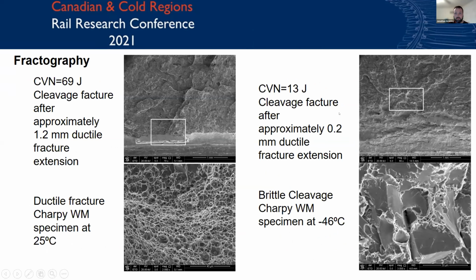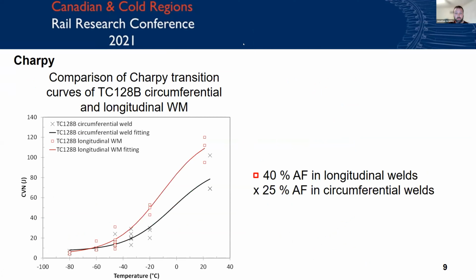So moving on, the next curve shows both the longitudinal and circumferential welds on the same figure, so we can compare them together. You'll see that the longitudinal weld that had 40% acicular ferrite had a significantly higher Charpy impact energy at most temperatures than the circumferential welds with 25%. So we think one major contributor to the performance of these welds was the amount of acicular ferrite that was present.